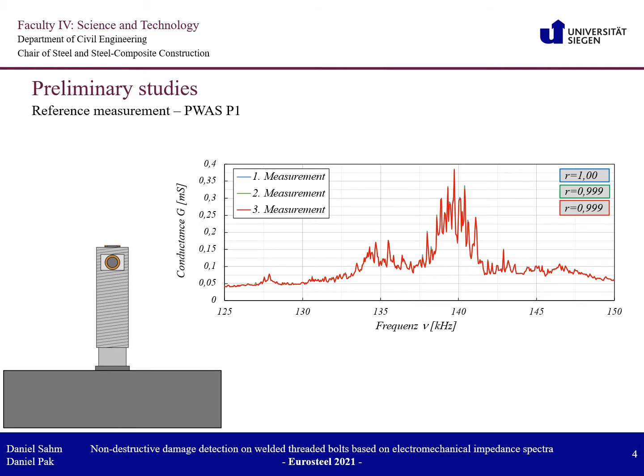The first thing I would like to show you is the results of our reference measurement. For the reference measurement, 3 measurements were carried out one after the other. The results can be seen in the diagram. The conductance spectra over the frequency range from 125 to 150 kHz are shown here. It can be seen that the spectra hardly change if the conditions remain the same. The correlation, which served as a damage indicator in all tests, also remains almost at 1. This shows the reproducibility of the measurements and helps to better interpret the results from the other preliminary tests.